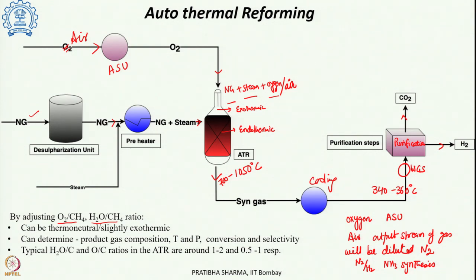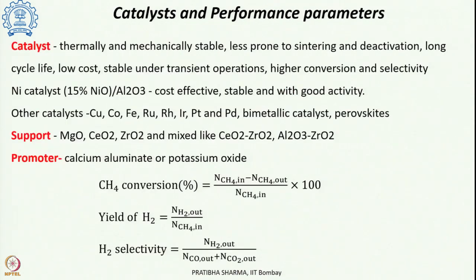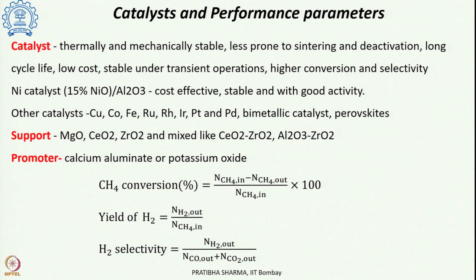The product gas composition, as mentioned, will be dependent on temperature, pressure, the conversion and selectivity of the process, and the typical steam to carbon ratio or oxygen to carbon ratio which are used in the autothermal reformer are a steam to carbon ratio of 1 to 2 and an oxygen to carbon ratio of 0.5 to 1. Now, since the process has more CO2, there are combustion products, and the conversion and selectivity can also be selectively preferred towards the desired H2 by CO ratio using the appropriate catalyst support and promoters.